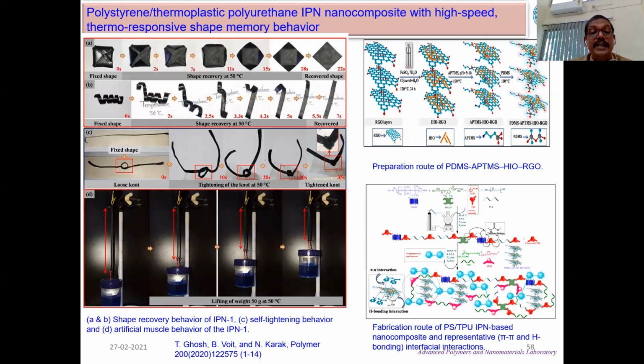And these polymeric nanocomposites can also form within 35 seconds this self-tightening knot. This also has the artificial muscle-like character, like it can lift the weight at about 50 degrees centigrade - 50 gram weight can be lifted by this change of shape using this polymeric nanocomposite. That means it has artificial muscle-like character.